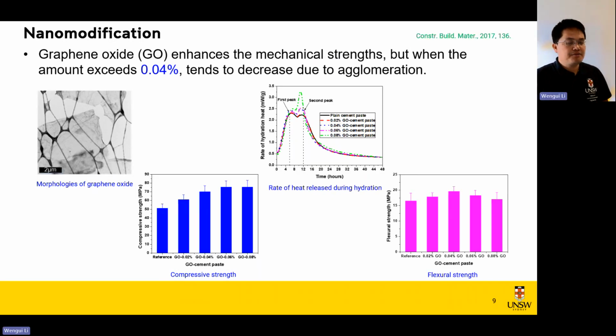Now, let's look at the effect of graphene oxide on the cement hydration. So basically, we can say the cement hydration is accelerated. As a result, the mechanical strengths are improved correspondingly. But when the amount of graphene oxide exceeds 0.04%, we can see there is a decrease in the flexural strength, as you can see from here. And this is due to nanomaterial agglomeration.